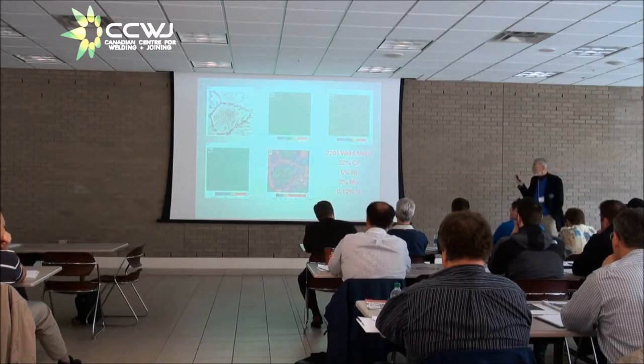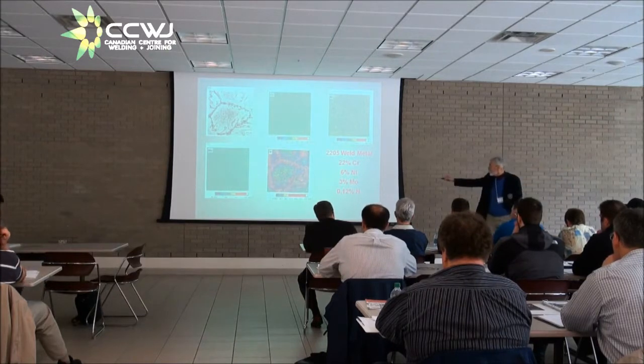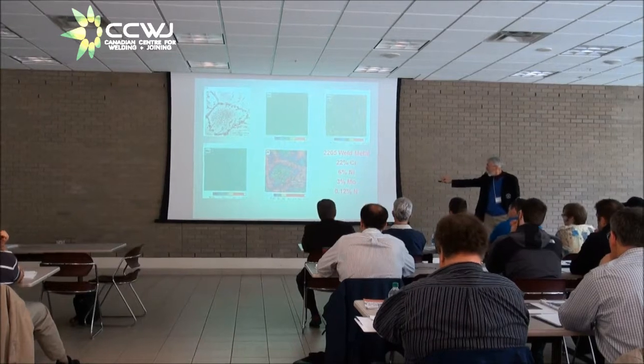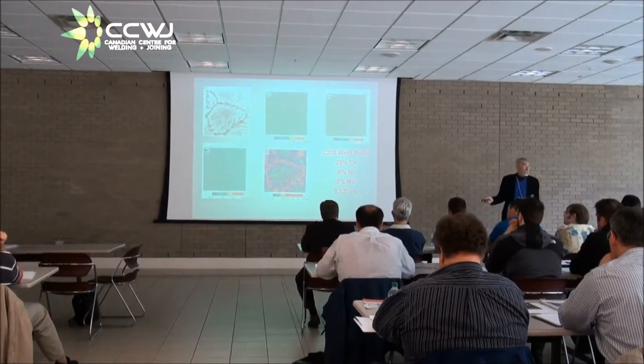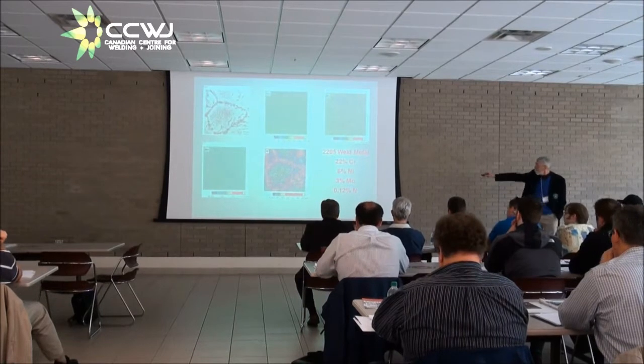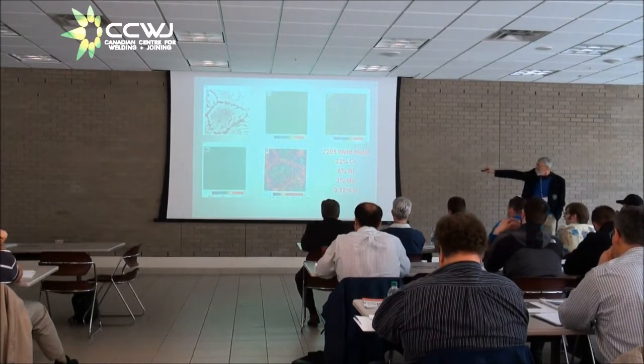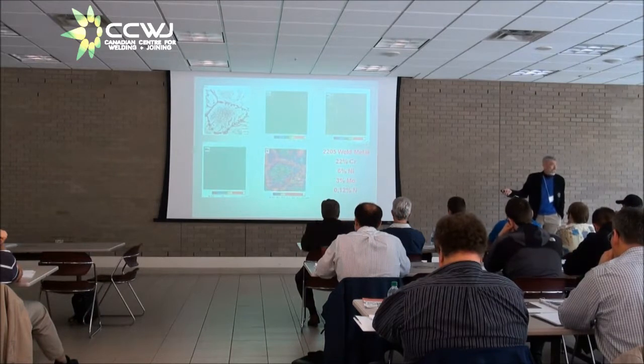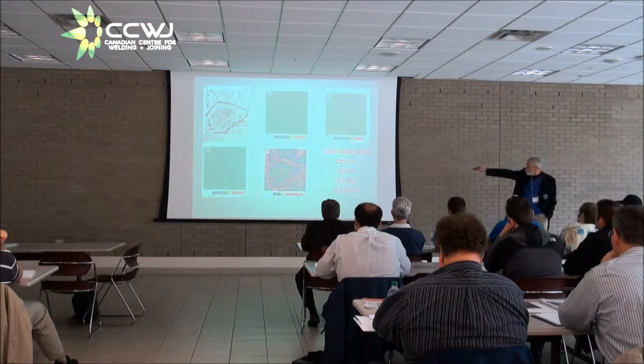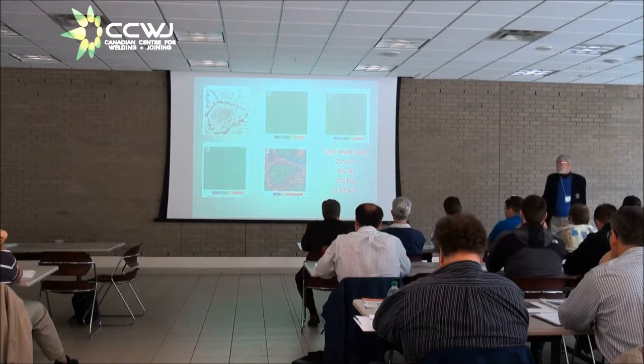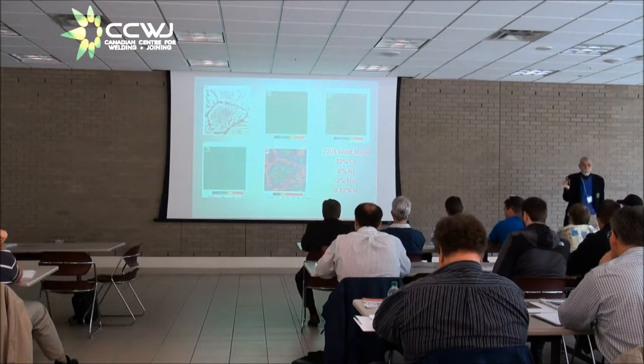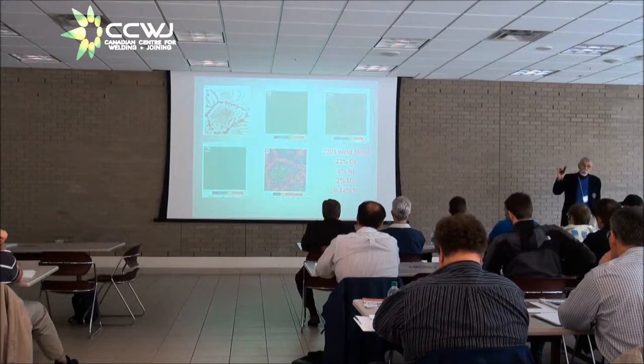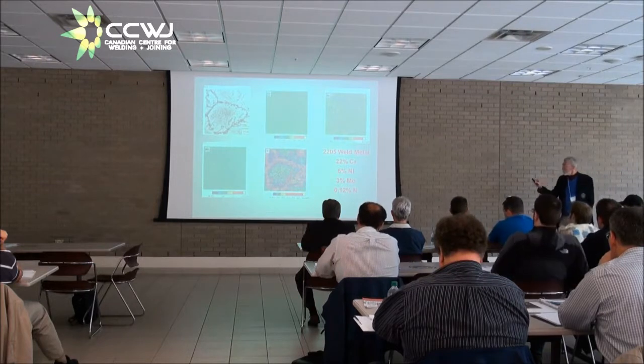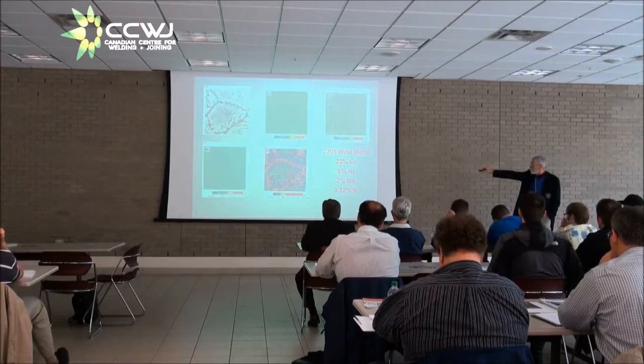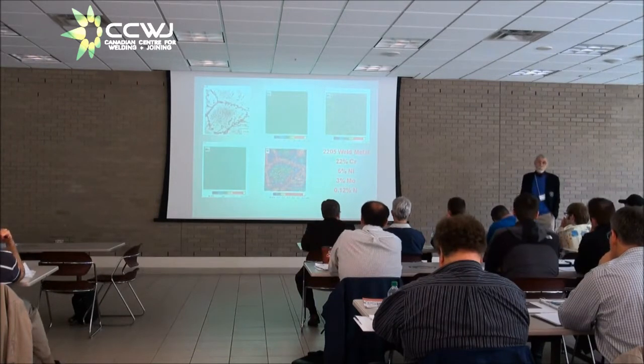However, when you look at the nitrogen distribution, you can see the ferrite grain very clearly outlined by nitrogen, which is in the austenite plates on the grain boundary. You can see in the center of the grain an essentially nominal nitrogen content that's caused by a mixture of chromium nitrides and ferrite. And next to the grain boundary, you can see the zero nitrogen blue color, which means the nitrogen had a chance to get out of there. So nitrogen was diffusing towards the austenite out of the ferrite. Near the grain boundaries, the nitrogen can get out, but in the center of the grain, it can't. It doesn't have enough time.